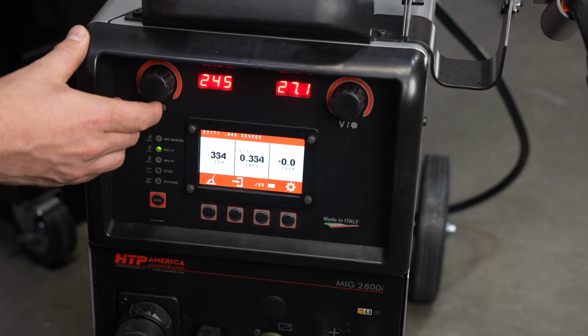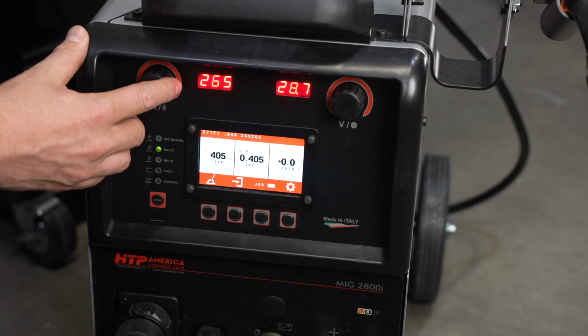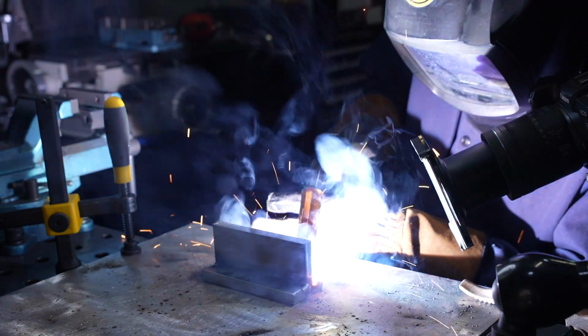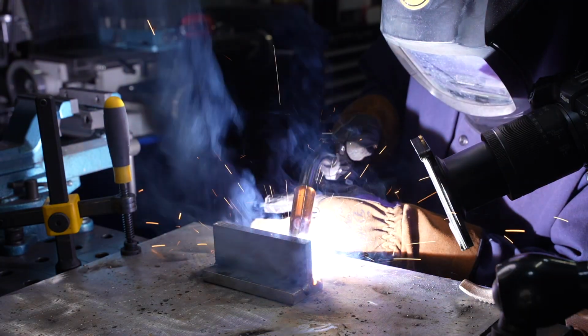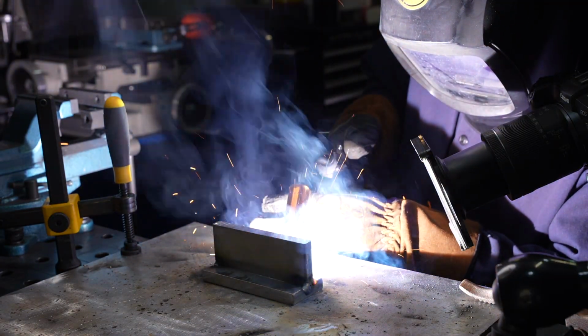Now I want to try something just a little bit thicker, so I'm going to go ahead and turn up my wire speed, and that'll increase my amperage as well, and then run here on some 1/2 inch thick plate. Notice once again, I'm just using that very slight drag angle. The biggest thing is to keep those angles very consistent as you weld along.